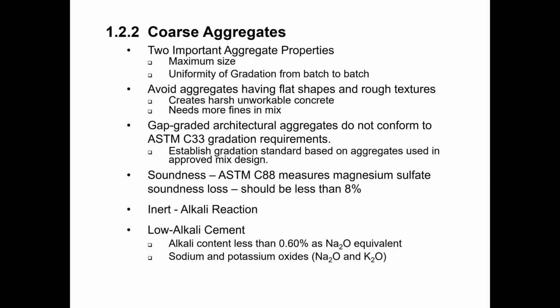So generally, these two materials have different molecular weights, and so we normalize the potassium molecular weight to the sodium molecular weight, and so it's reported as a Na2O, or sodium oxide equivalent. So as long as that sodium oxide equivalent is less than 0.60%, then the cement can be classified as a low alkali cement.